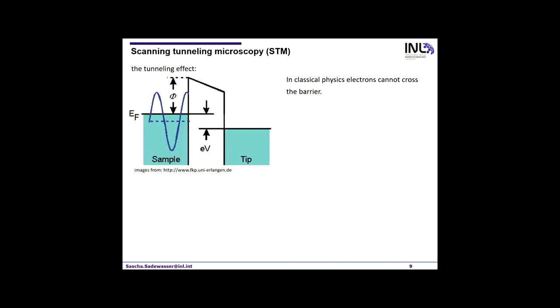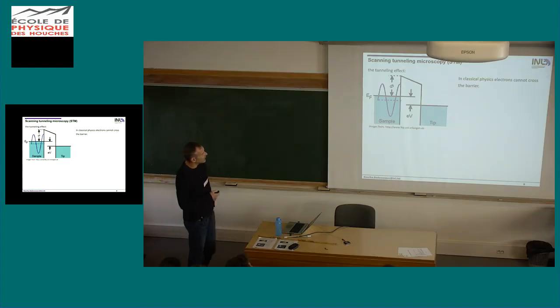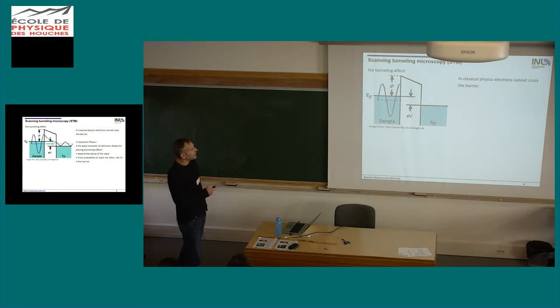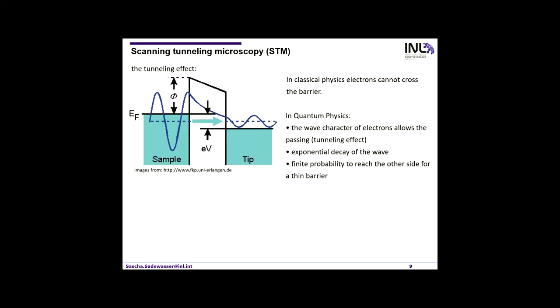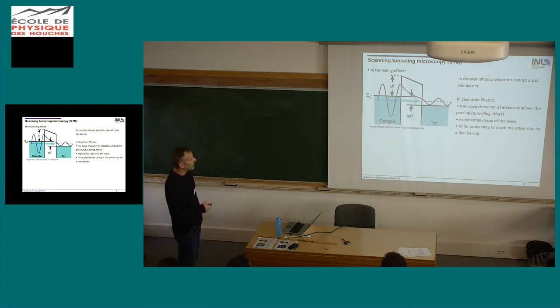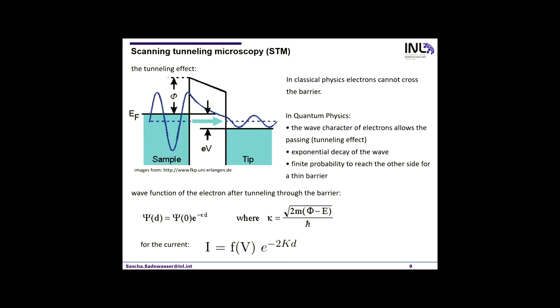This is done employing a quantum mechanical effect, which is the tunneling effect. If you have your sample and your tip, then in classical physics, the electrons from the sample could never cross this vacuum barrier here. However, in quantum physics, the electron has a wave character, and there's an exponential decay of the wave function of the electron that reaches out of the sample and can, if the tip is close enough, actually enter into the tip. That means there's a finite probability to reach the other side of the thin barrier.